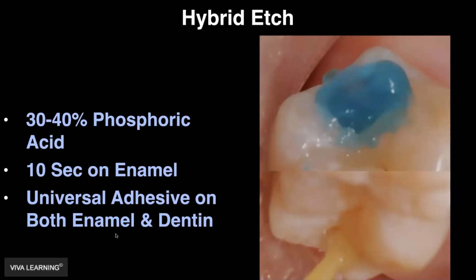So hybrid etching is actually a technique where we're going to use phosphoric acid, and we're going to just put it on the enamel only, and we're going to let it go about 10 seconds on the enamel. Then we're going to rinse and dry. We're never going to put phosphoric acid on the dentin.